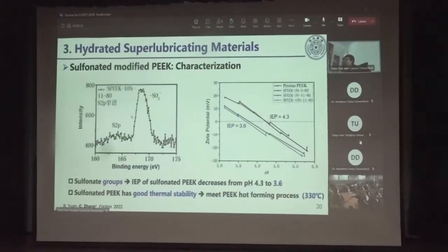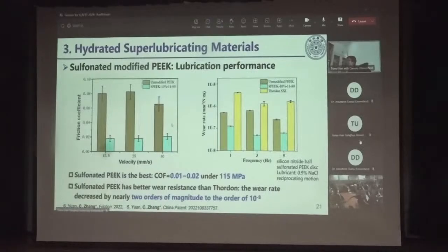First, we analyzed the modified PEEK by XPS and found this sulfur element peak from sulfonate in this spectrum. That means the sodium sulfonate groups were grafted on the PEEK powder. And then we also measured the zeta potential of the surface for the modified PEEK, the blue and the green one. The zeta potential decreased compared with the red and the black one, which are unmodified. So that means there are more negatively charged sites on the surface in water after modification.